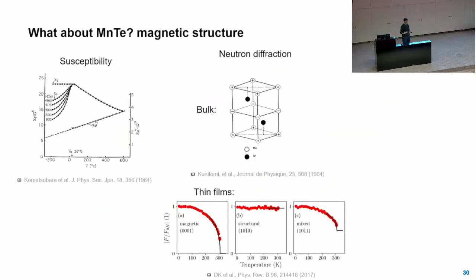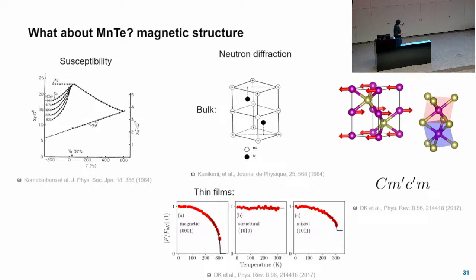That's actually the first thing we had to do. We had to understand the magnetic structure. And in fact, it was reasonably easy, because there's already, let's say, 60 years of research on that material, and so we know reasonably well what the magnetic structure is. And we did some more work on that in the form of thin films a few years ago, and we figured out, okay, the magnetic structure looks like this. So we have half of the manganese atoms with the magnetic moment, their spin pointing to the right, and half of them to the left. And that's why I draw them red for one case and blue for the other.